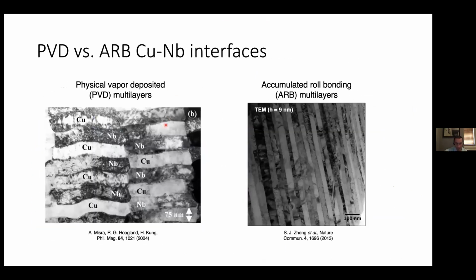So if you look closely, here are some 3-point contacts between copper-niobium interfaces in this multi-layer composite made by PVD. And you can see how there's a contact angle. So there's this interface here, and then there are these two interfaces here. By measuring those contact angles, you can figure out the relative energies of those interfaces. And if you can calibrate at least one of those interface energies, then you can figure out the other ones. That's typically how people have done it experimentally. Right. Thanks. More questions?